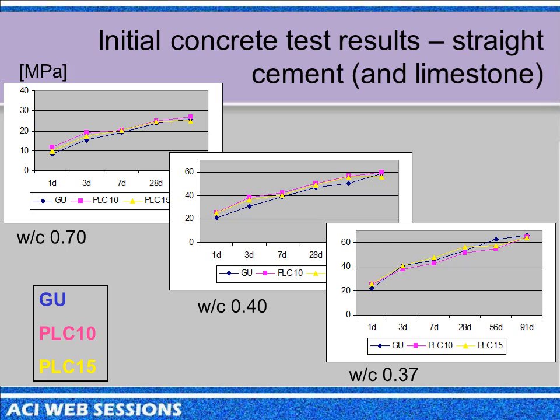This is one of the company's trials with various water cement ratio concretes. The straight Portland cement is the blue, 10% limestone, 15% limestone. 15 is yellow, pink is 10. And you can just see, even with 0.7 water cement ratio concrete, there's no influence on the strength development performance, 1 through 90 days here. And in fact, in some of these mixes, there's a slight enhancement. Sorry, these are in metric units, but you're looking at about 3 or 4 megapascals, 500 extra PSI, even at 1 day, from the limestone cements over the Portland in that case. But again, they're very similar in performance, so you're not seeing a technical change.